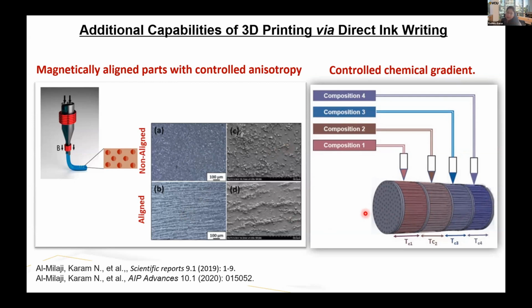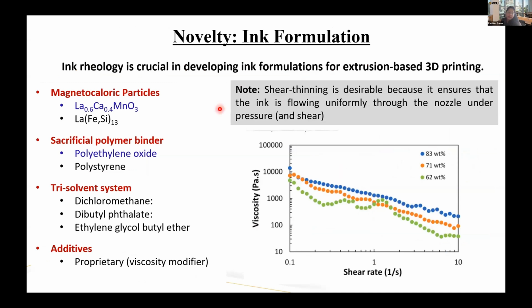With that in mind, we've done studies with magnetocaloric particles that are LCMO—these are oxides—as well as lanthanum iron silicides, with the selection of binders. We have a patent on the ink, where we worked with a certain ratio of 3 solvents and an additive which is proprietary because it is patented.